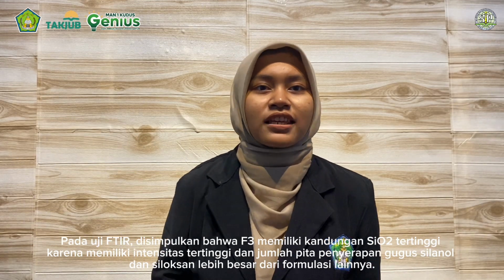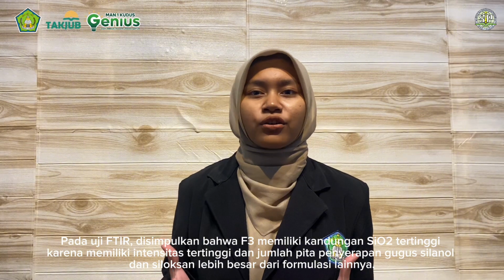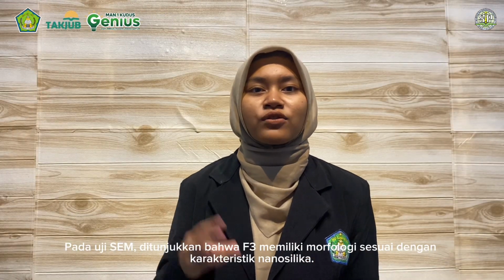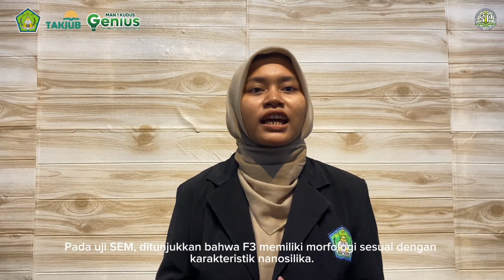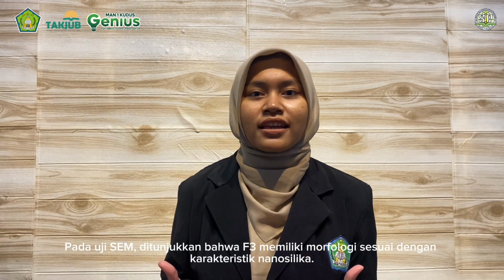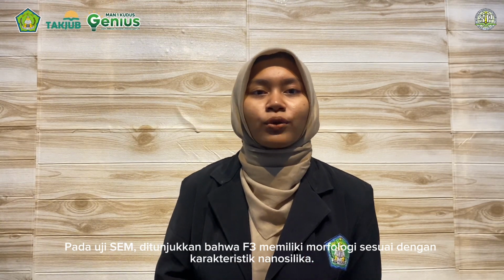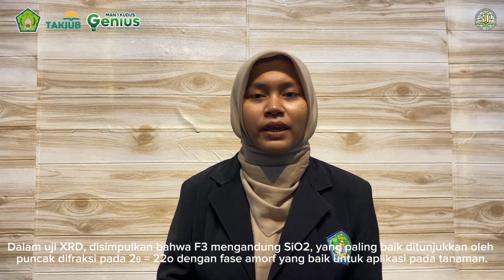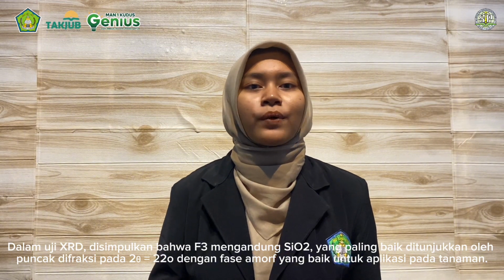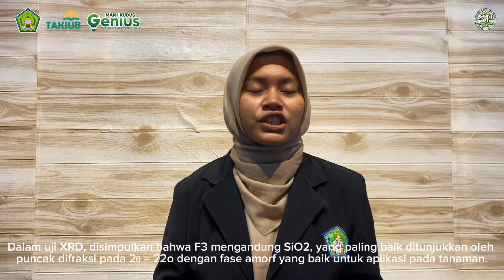In the FTIR test, it was concluded that F3 has the highest SiO2, and in the SEM test, it was shown that F3 has a morphology according to the characteristic of nanosilica. In the XRD test, it was concluded that F3 contains SiO2, which is best shown by the diffraction peak at 2 theta of 22 degrees with an amorphous phase that is good for application to plants.